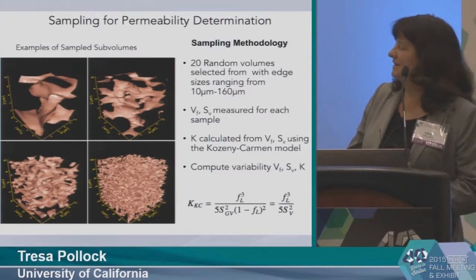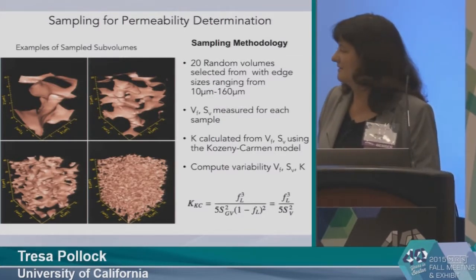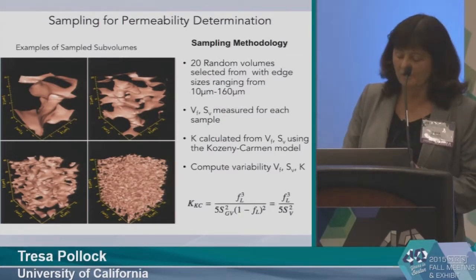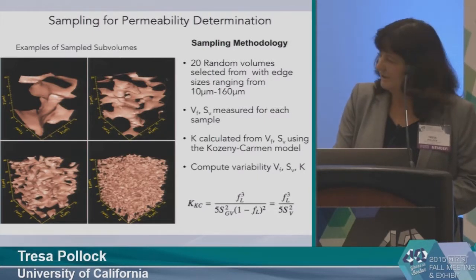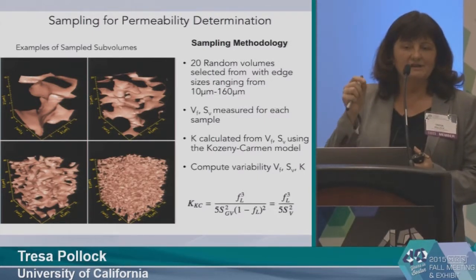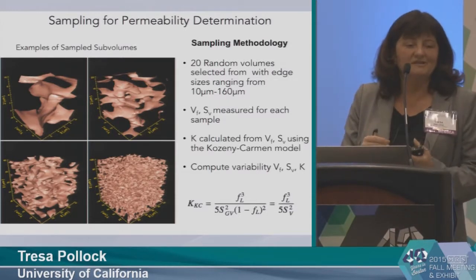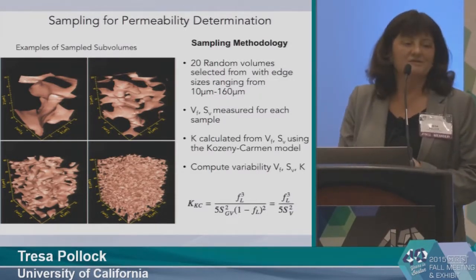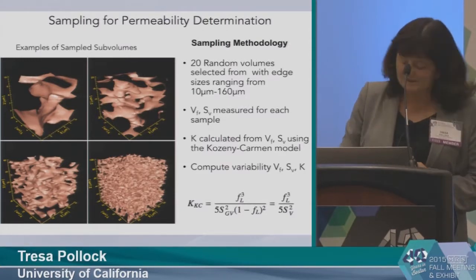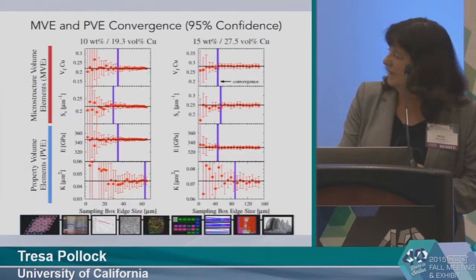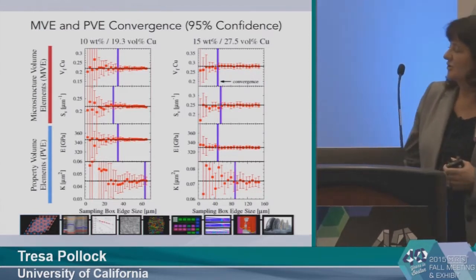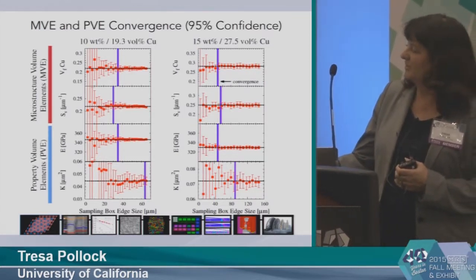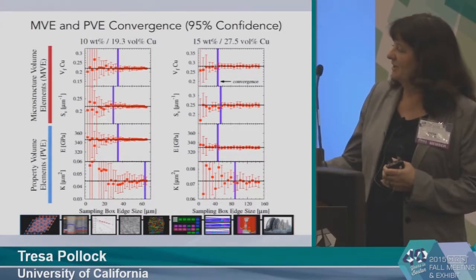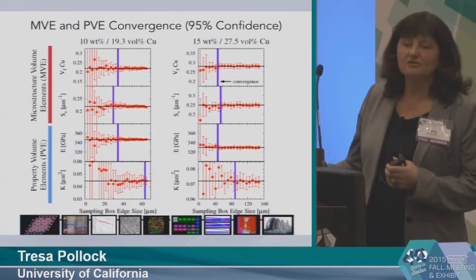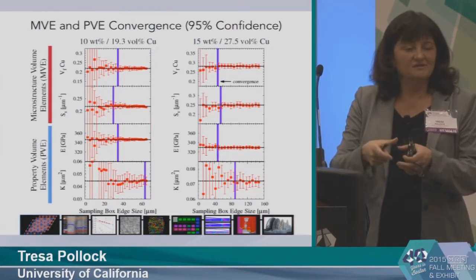And what I'm doing is changing the sample size and then calculating, in this case, the permeability, because that will be important to the infiltration of the copper. Now, for engineering properties, we don't just need kind of a mean prediction. We need statistics, right? Real engineering systems designed based on minimum properties. And so what we're trying to do here is build a methodology for doing that. And so what I show here on the property end, the modulus and the permeability, and I'm showing these properties as a function of the sample size that was subsampled.